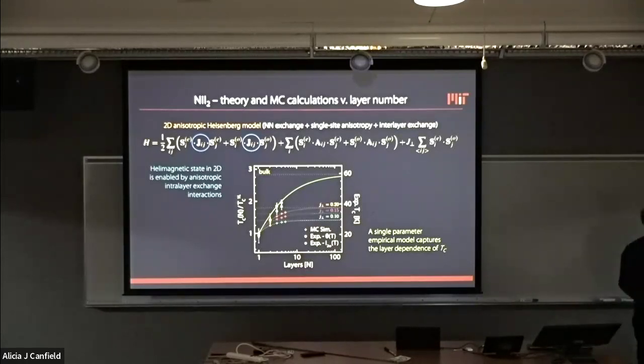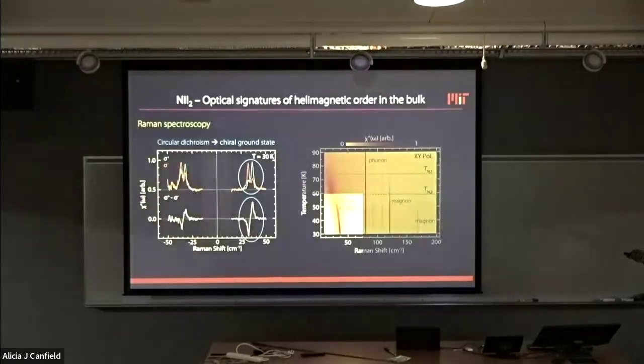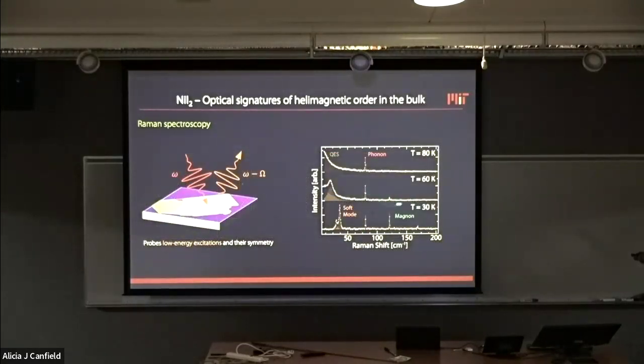Perfect. So when you do the Raman, I would expect that you're going to start seeing a bunch of other modes, or maybe a few other modes that were not Raman active. Now that you probe polarized, do you see them showing up? Yes, so there are a few modes that appear. There is a magnon mode that appears down low. This electromagnon is probably appearing because it's IR active, but it becomes visible now because of the polarization signature. Oh, so you think these would be, okay. That would be my guess, yes. Do you see modes that are folded, or zone-folded? You see magnon modes appear, but you don't see folded modes. Yeah, those are all the new modes that we see. Okay.